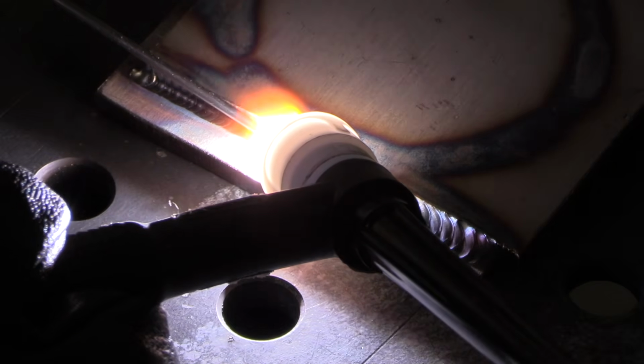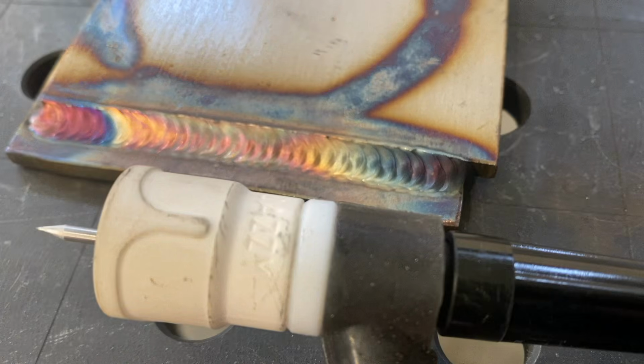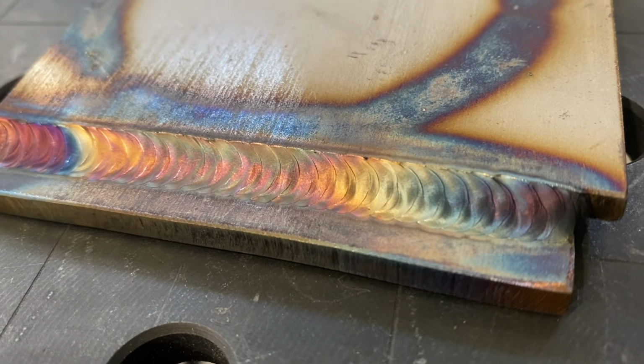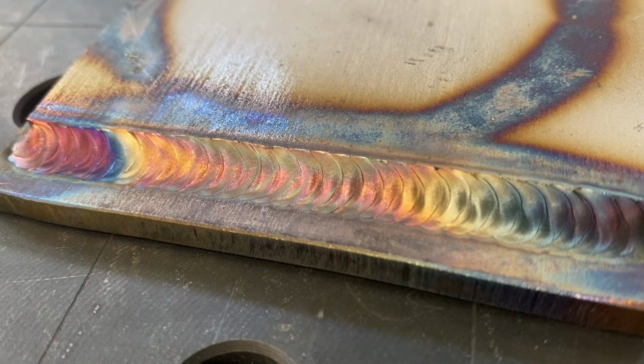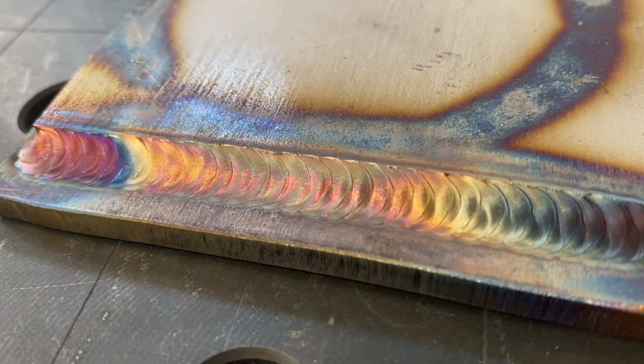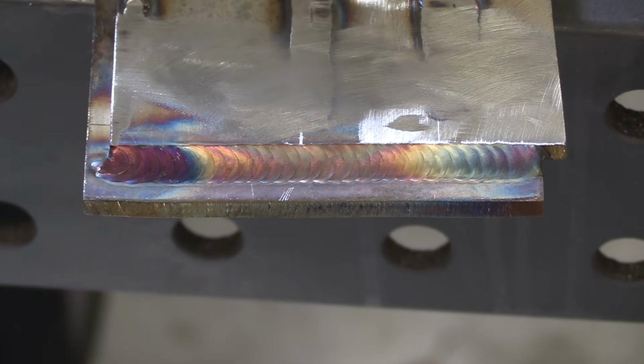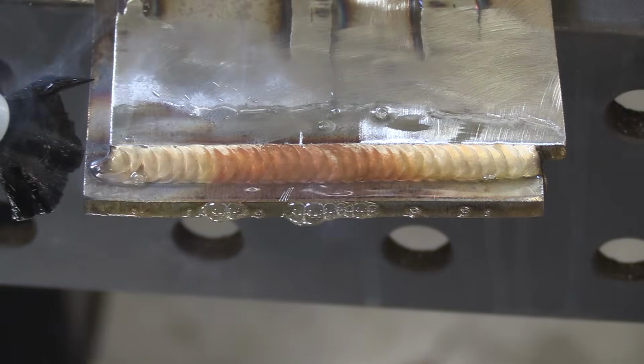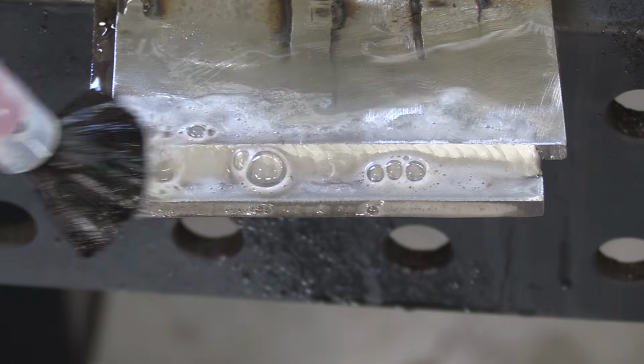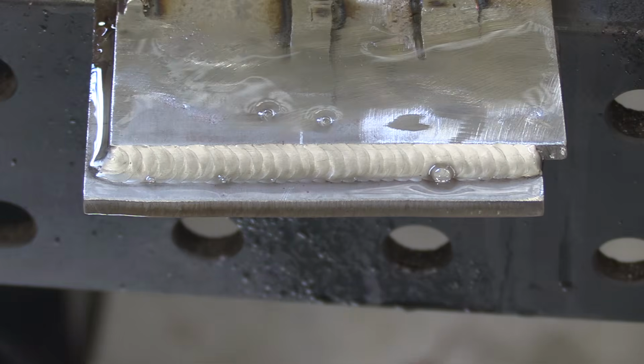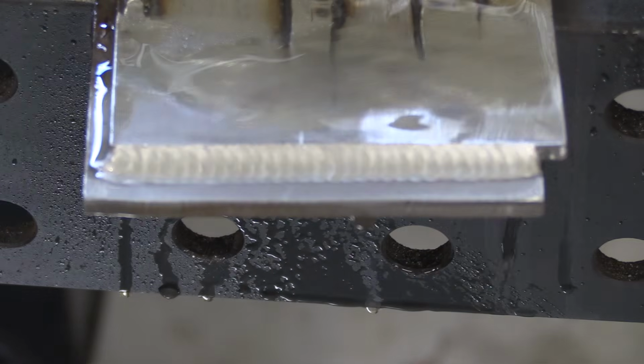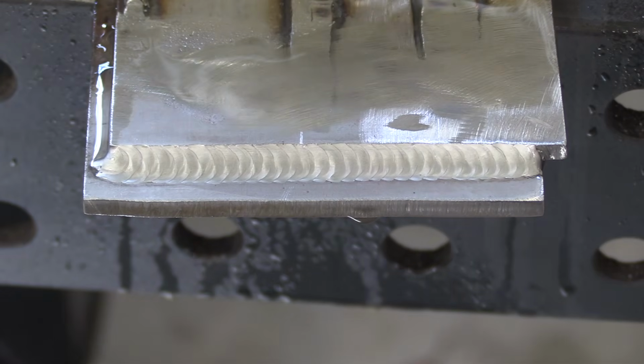This is the second pass on a 2-pass lap joint on 1/4 inch stainless steel. It's 304L stainless steel welded with 308L filler material. That's typical. Got some nice colors on that, but again, those colors don't mean anything. Those colors aren't very corrosion resistant. So let's take that same weld and hit it with the EasyKleen EK Plus. And that removes a layer of material, makes that surface layer passive and much more corrosion resistant.